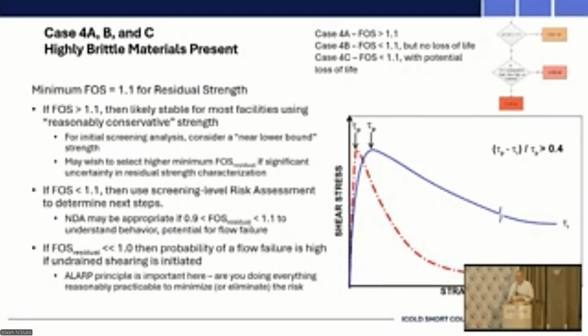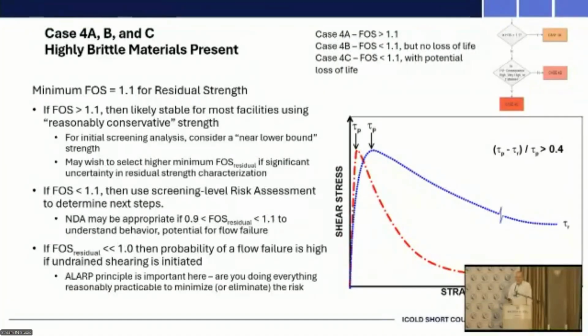And so it really drives home that in cases where you have highly brittle materials, understanding this residual strength factor of safety and really understanding the characterization, making sure you have a fairly high degree of confidence in your characterization. And if you do have a high degree of confidence and you still have a factor of safety less than 1.1, then you have a real problem that you have to address. So for initial screening analysis, it's appropriate to consider a near lower bound. What is near lower bound? I'm not going to tell you what the number is.